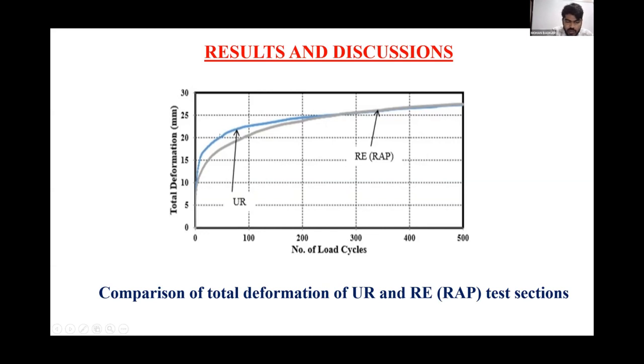Initially, up to 20 cycles, there is a sudden increase in the settlement. From 20 to 200, there is a transitional behavior in the settlement. After that, there is a gradual increase in settlement with the number of loading cycles.